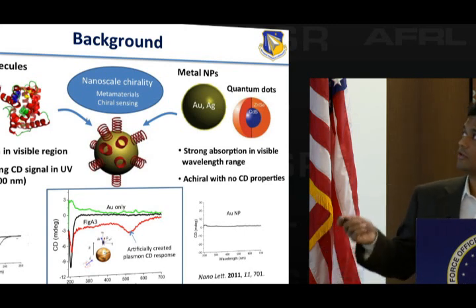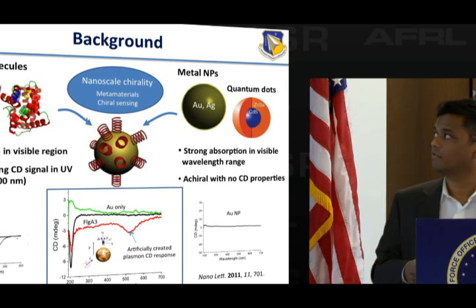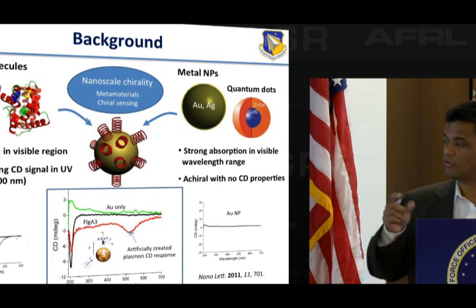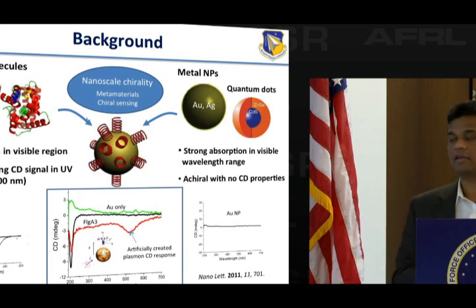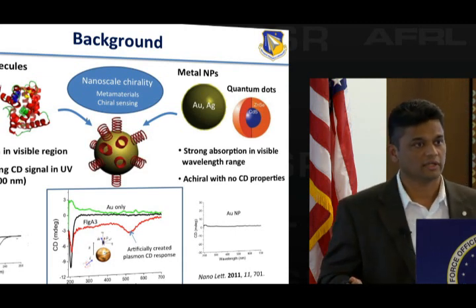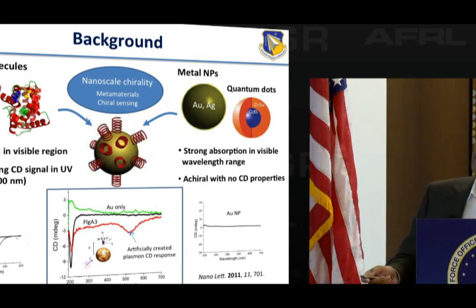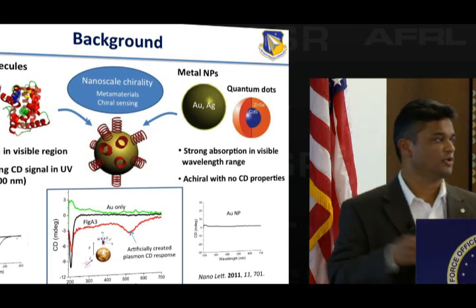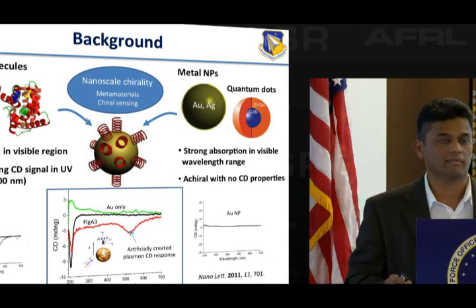Now, if I take a solution of nanoparticles, whether it's quantum dots, silver, or gold, put that into a vial, and you measure it, you pretty much get a flat line because it's achiral. You don't see any signal. But what we saw is that when I take that peptide and mix it with the gold nanoparticle, now I see the signal that comes from the peptide, but now the plasmon band of the gold nanoparticle also becomes chiral. So you're beginning to artificially create a plasmon CD signature when you combine the two materials together. We've never seen this.